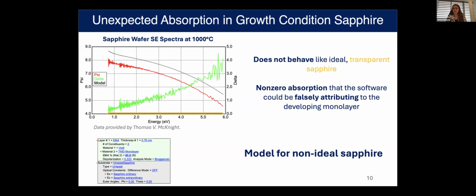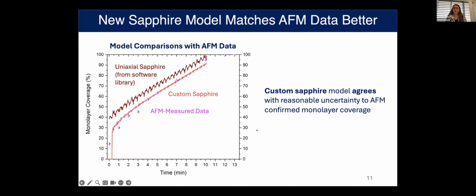So what I did was I made a custom model where I assumed that something non-ideal was going on with the sapphire. It wasn't entirely transparent. Applying that model resulted in this graph where we see this red fit for the custom sapphire, where obviously there's this vertical thing that's happening that's still a bit questionable. So at the low energy end or low time end, there's still something to look for and fix, but we got much better agreement with the AFM confirmed data.